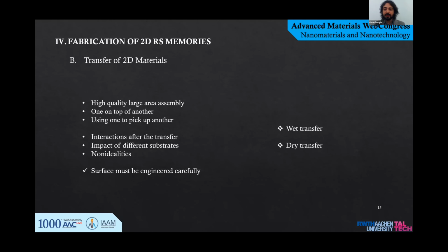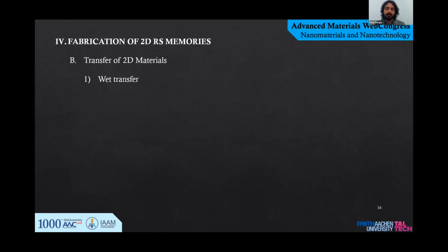Therefore, this surface must be engineered carefully for stable and reliable results. And although wet transfer is easier to do, results may have imperfections, causing undesired effects on some properties of 2D materials. Dry transfer methods were developed to resolve those issues, and they use different materials along the way. The wet transfer of grown 2D materials was developed as a more controllable and scalable process due to the Scotch tape method's limits on large-scale manufacturing.